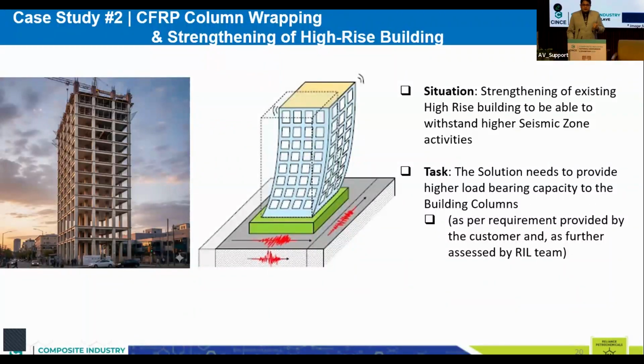Carbon fiber, with its tensile strength 10x that of steel, with its modulus almost equivalent to steel, and density 1/5, eliminates all these problems, not only by providing the strength, but at almost 1/10 of the thickness of comparable steel, and at a weight penalty which is negligible. So there is no dead weight penalty on the tall structure.